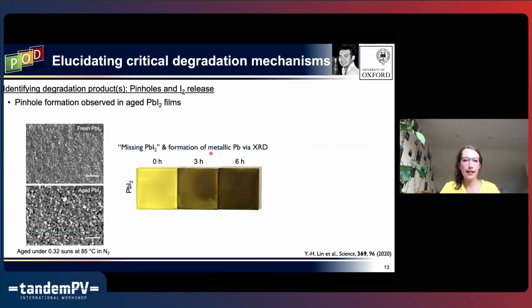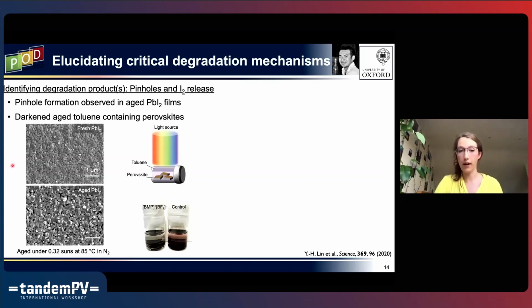So one of the things that we looked at next was related to pinholes. If we take just lead iodide and expose it to light at elevated temperatures, you start seeing pinholes in the film. In XRD, you can start seeing metallic lead. And so you would assume from just the lead iodide type films that you're losing I2. So he looked at figuring out, is that actually happening in the perovskite film, or is that just something that happens with lead iodide? In this experiment, the perovskite films were put into a sealed vial filled with toluene, and then they were exposed to light.